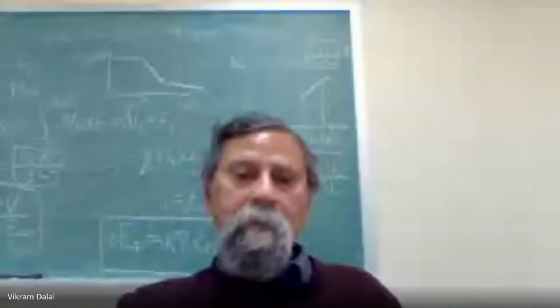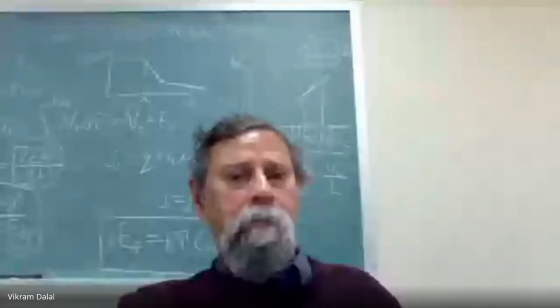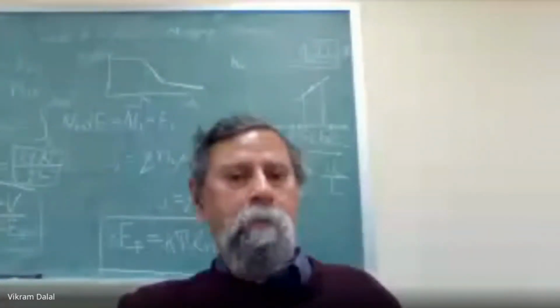And you can see the influence of ions. If you plot the dark IV curve before and then immediately after exposure, you don't get zero current at 0 volt. You get zero current at about 0.25 volt. And at 0 volt, there's a finite current, a negative current. Why is there a negative current at 0 volt? That's very strange. Because the iodine ions are moving.